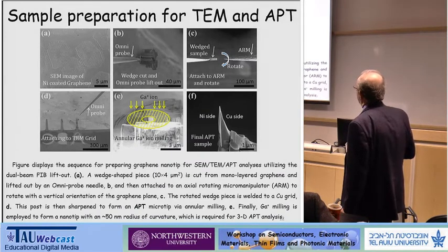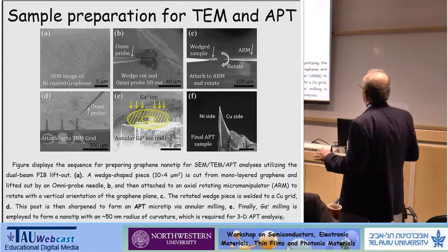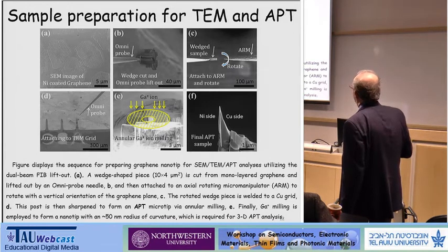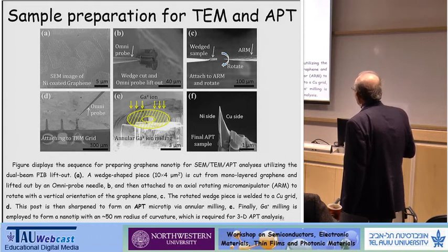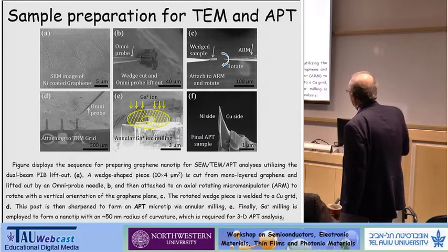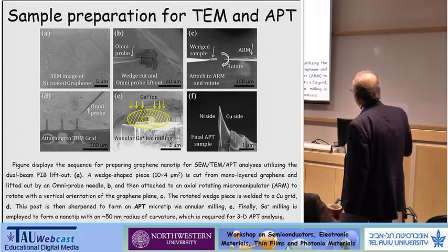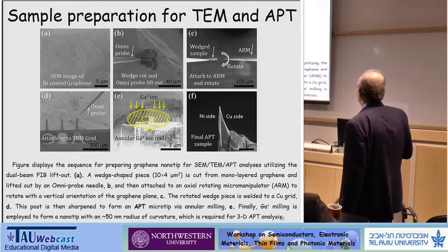So here's how you make the specimens. I showed you this SEM micrograph already. On top of the specimen, nickel is deposited. Then with the dual beam FIB microscope, we mill out a specimen that has a triangular cross-section. So it's a wedge-shaped specimen, and you pick it up with an Omniprobe, and then we use what's called an ARM, which allows us to rotate the specimen and align the interface along the long axis of this nanotip. We can also put the specimen on a TEM grid first, to analyze it using transmission electron microscopy, and then ion mill it into the shape of a nanotip. And this is your specimen. You can see the nickel side, the copper side, and this dark line here is the graphene.